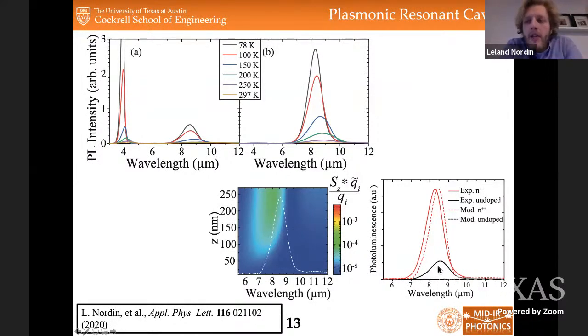On the left is the control structure, wherein we grew the T2SL on top of an undoped substrate. And then on the right is the T2SL grown on a highly doped substrate. And you can see we actually get better photoluminescence, suggesting our optical quality is as good, not necessarily better, because the actual physics for why we see an enhancement in photoluminescence is due to the resonant cavity and then also the additional photonic density of states from the SPP mode.